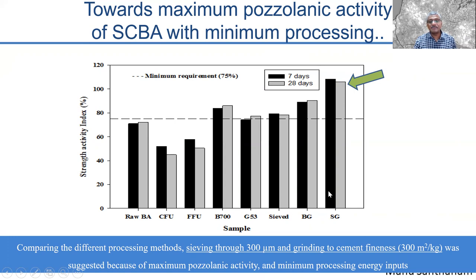And interestingly, sieving and grinding to cement fineness. That's what you'd expect when you actually take this bagasse ash and mix it with the clinker and put it in the ball mill. The grinding will lead to the production of uniform sizes. Of course, that depends on the relative hardness, but a siliceous material like bagasse ash may not have that much difference in hardness as compared to the regular calcium silicates that you have in the cement.